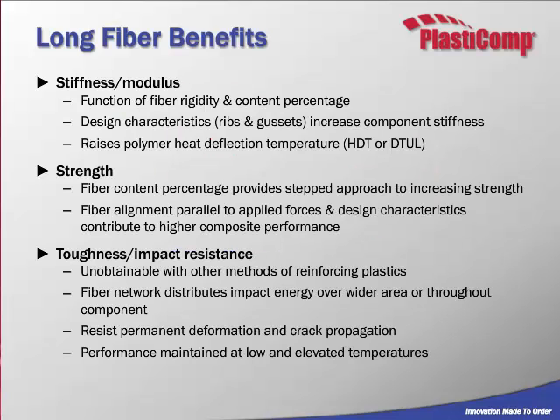So why long fiber? The main benefit that you'll get from long fiber is a large increase in impact resistance, especially when compared against short glass. With both short glass and long fiber, by just inputting that fiber, you're going to get an increase in modulus. So that's more a function of the filler content. And the higher you can go in filler content, the stiffer the material will be.